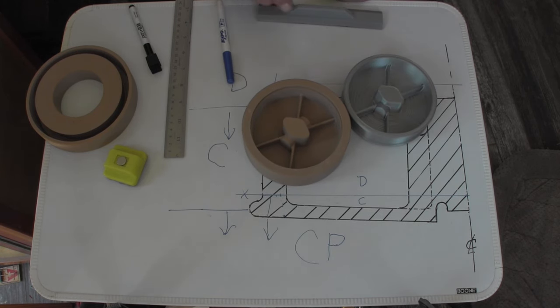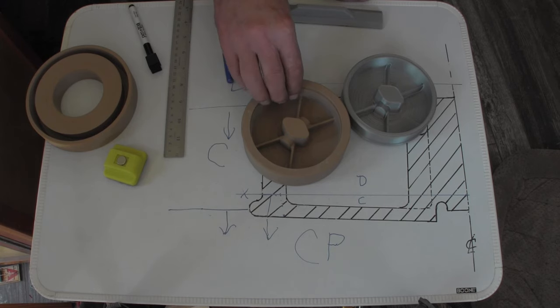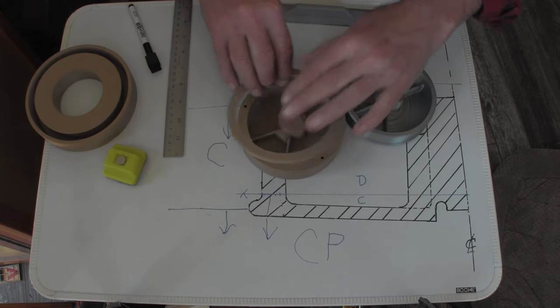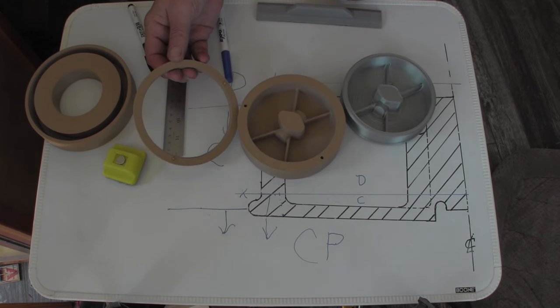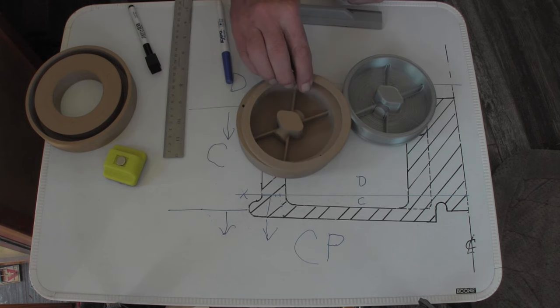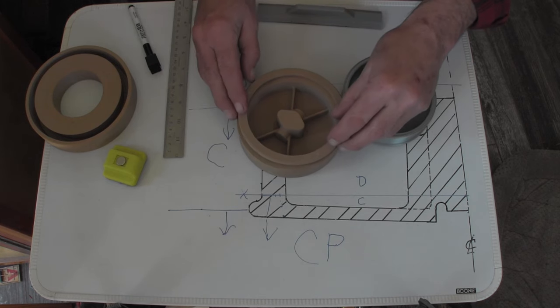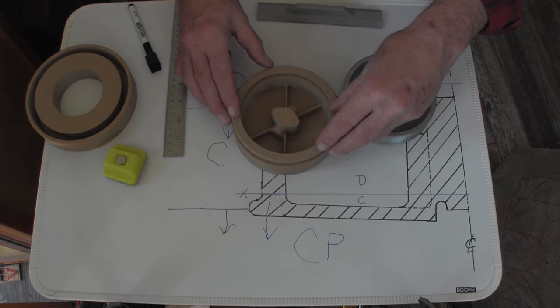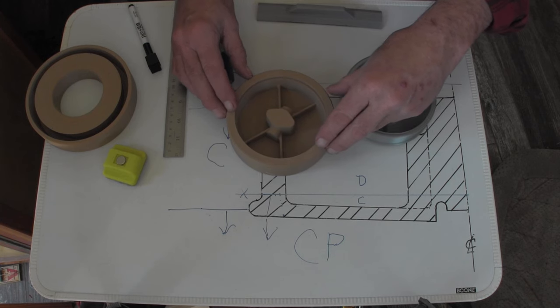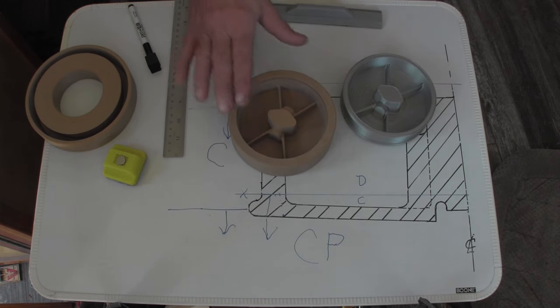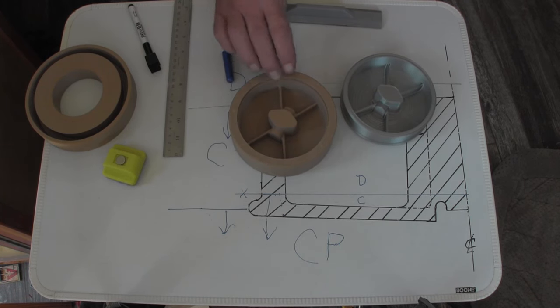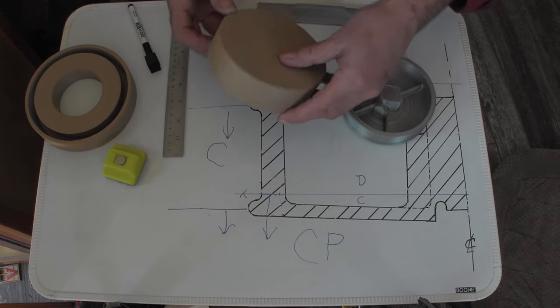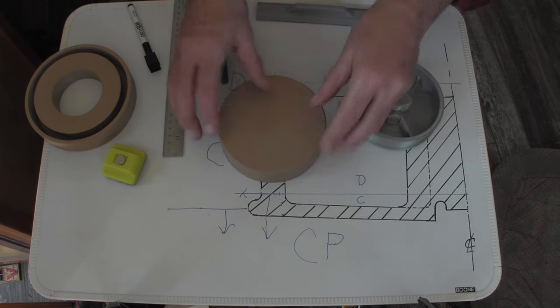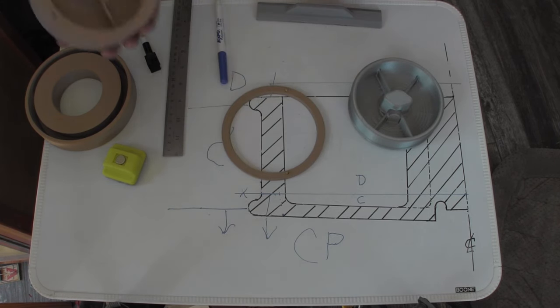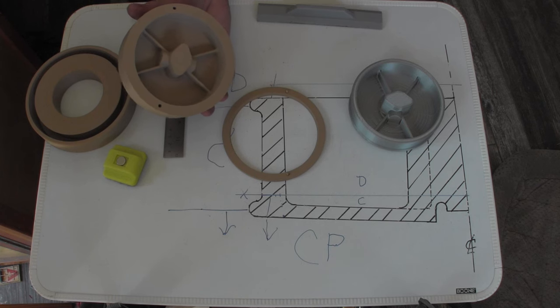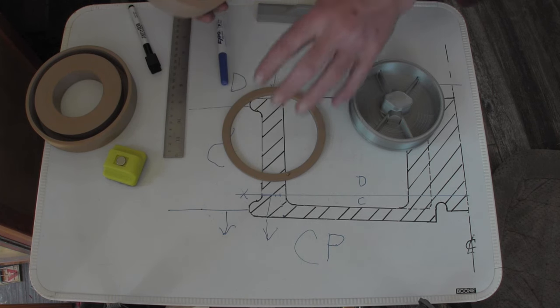So you got the core, but because you got reverse draft here, you have to make a loose ring like this. So you ram the core up with the ring on it, take the ring off, or actually what I'd do for me, I'd ram it up like this all the way to the top of the ring. Flip the entire core over, rest it on the ring, and lift this part of the core print or core box off, leaving the ring like that.